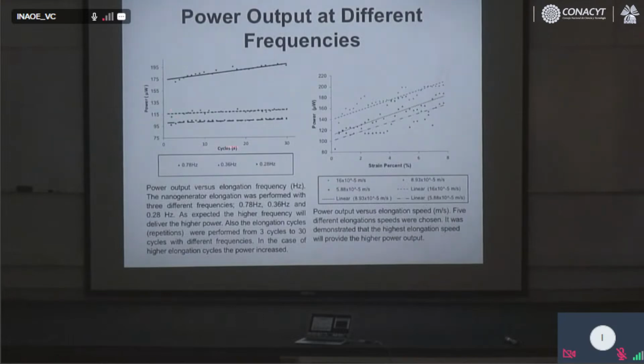Now, what we observe here are the cycles of stretching. And we observe that if we use different frequencies, we use very low frequency, because this sensor is intended to stay somewhere on your neck or here or somewhere, so the body cannot produce very high frequency. If the frequency is very low, the power output is smaller, and if you have a little bit higher frequency, the power output is a little bit higher. And then we look also at the speed. You can stretch a little bit slow or a little bit faster, and the highest speed will produce the highest power, but we cannot go more. Whatever we did, we wanted to get higher than 200 microwatt, we cannot.